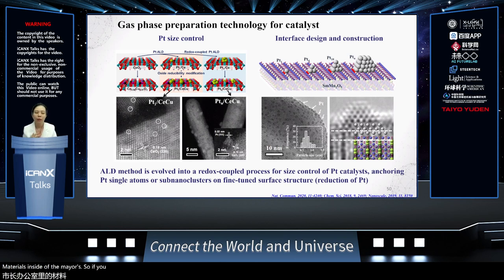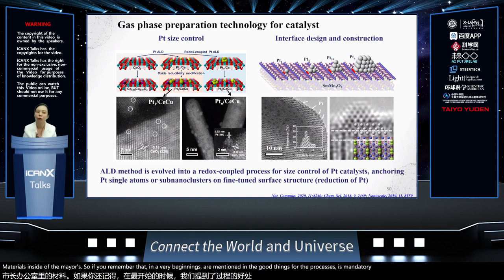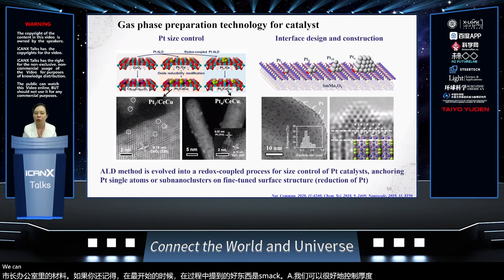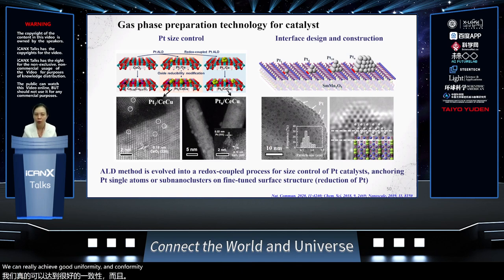If you remember, in the very beginning I mentioned the good things about the process: we can control the thickness very well, we can achieve good uniformity and conformal coatings, and we can tune the composition very well. Like here, in these two cases we can utilize ALD to tune the percentage of the incoming metal atoms. And we can also construct single atoms or metal nanoclusters very well.